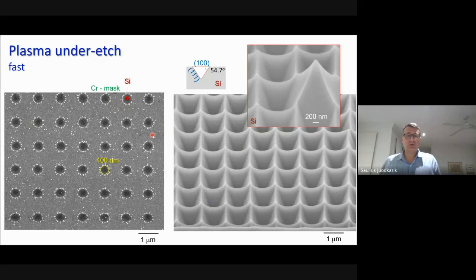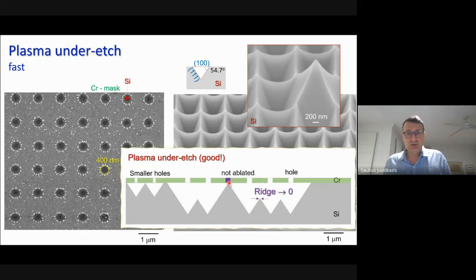And then after plasma etching, we have a nice pattern of pyramids etched on the surface below the openings of those holes in the mask. What is also good is that even if you over-etch, those pyramids are not disappearing or damaged. They simply go deeper to a new level, but they do not change the pattern. Sometimes there is no ablated spot in the mask, which is what happens here with the pyramid looking upwards, but this also proves that etching below the mask is not damaging the structure. So it's very welcome for large area fabrication.